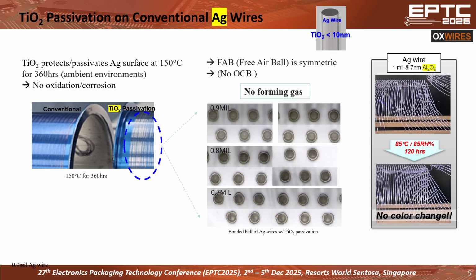However, after we apply a TiO2 passivation on the surfaces of the silver wire, where you're seeing the blue color, even after the harsh conditioning, you're going to get a very nice FAB, free air ball, symmetric ball shape. No OCB, even when no forming gas was used. You're looking at a 0.9 mil diameter of the silver wire with a TiO2 passivation, and a 0.8 mil diameter and 0.7 mil diameter as well. No forming gas was used.